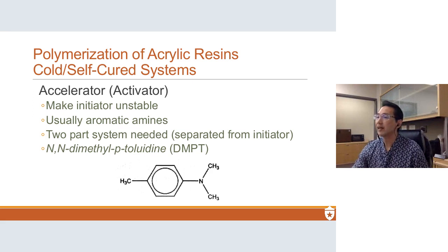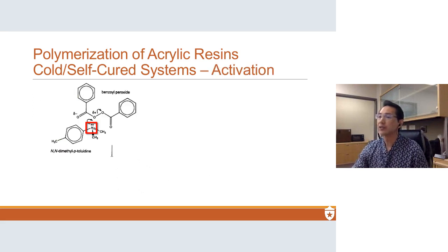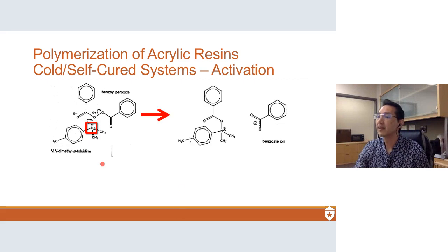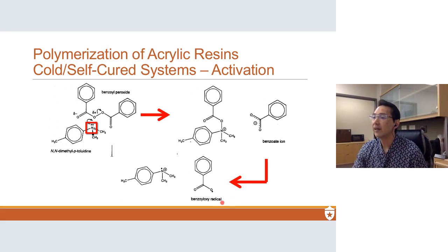So as far as the reaction is concerned, and we've seen something similar, I think, in just bullet form before, you have DMPT here with a lone pair of electrons on the amine. And that lone pair of electrons is what attacks the oxygen-oxygen bond here for the benzoyl peroxide. And then it forms a complex, and you get a benzoate ion being given off. And then that dissociates, and you end up with the benzoyloxy radical. So this is what then enters into the polymerization as the initiator system.